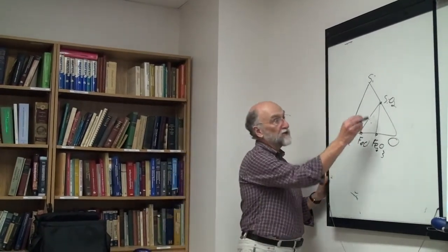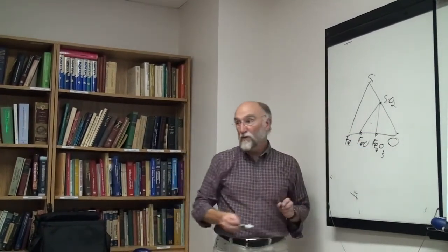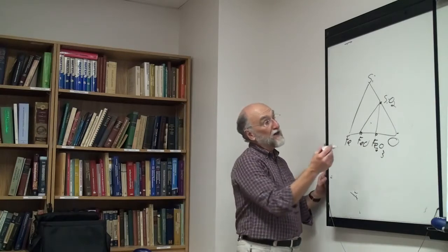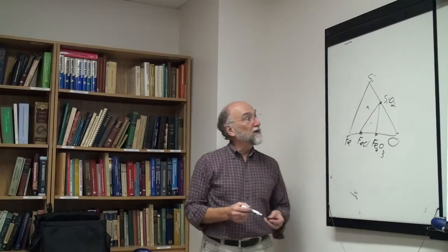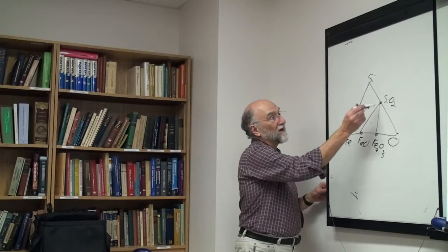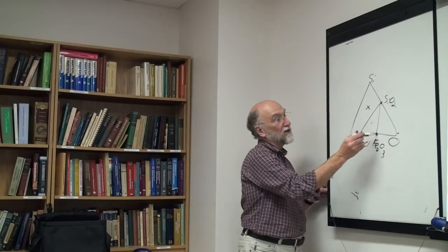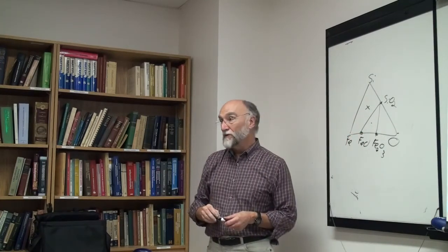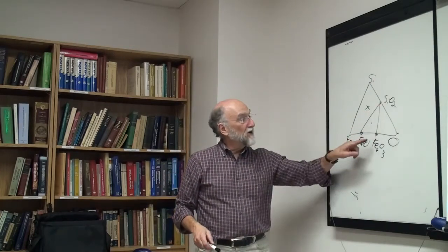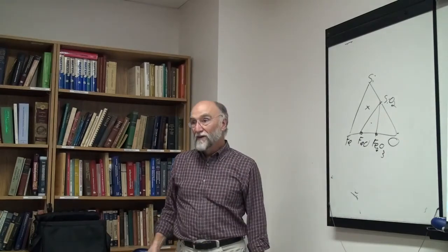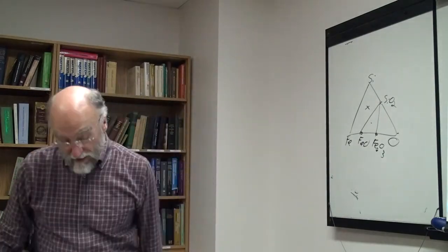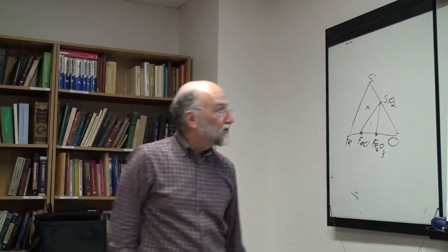So I could use these three components, or I could use these three components. It's arbitrary. You can even define a composition out here in terms of these three components, as long as you're willing to have a negative amount of Fe2O3, which is okay within the phase rule. You can have silica, FeO, and a negative amount of Fe2O3, which would put you over here, and you're still okay. So there are many different ways to arbitrarily define the components of a solution.